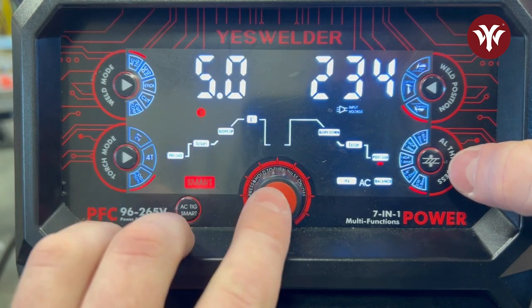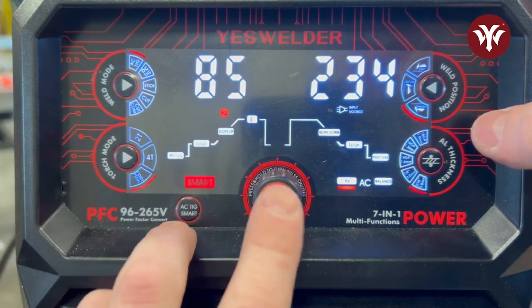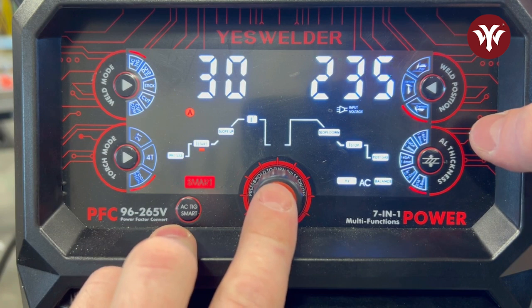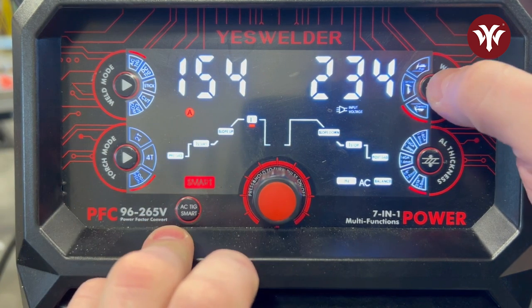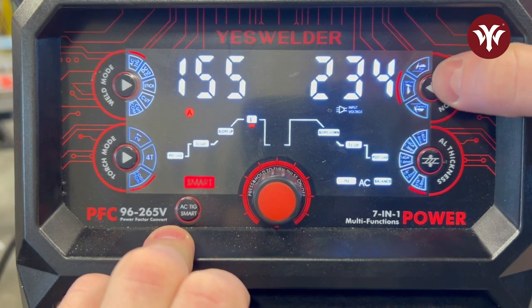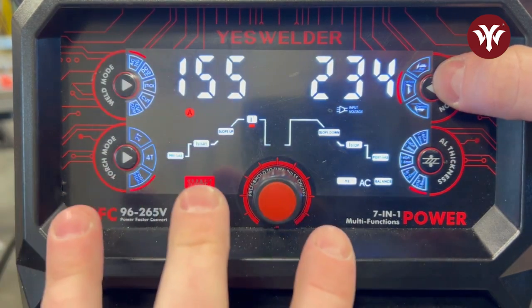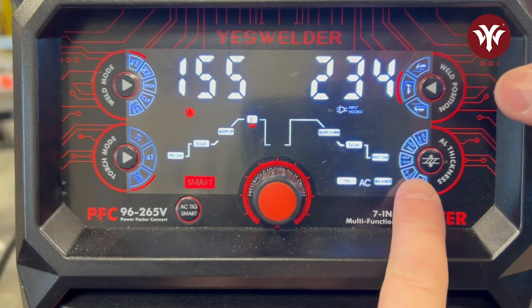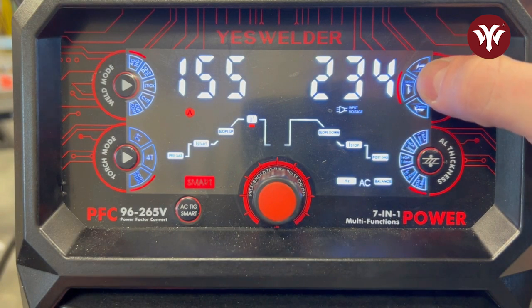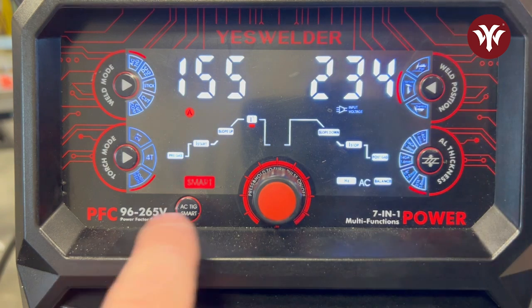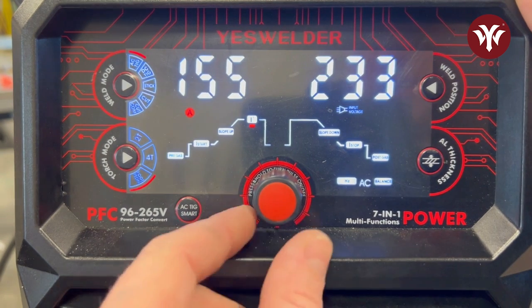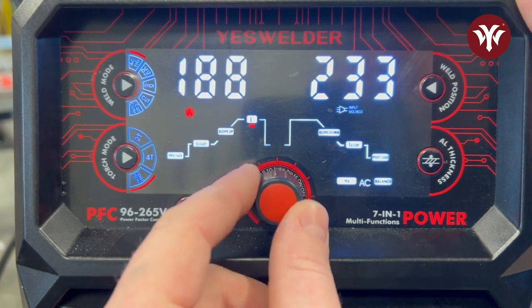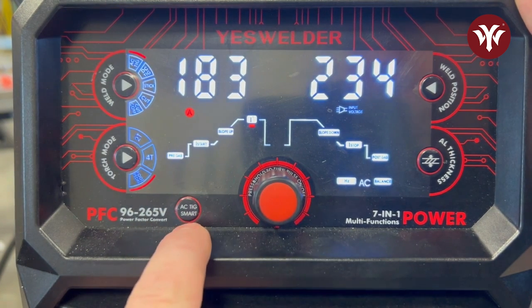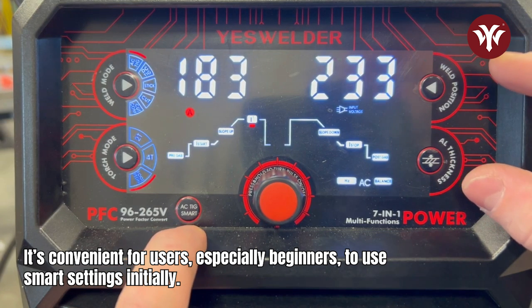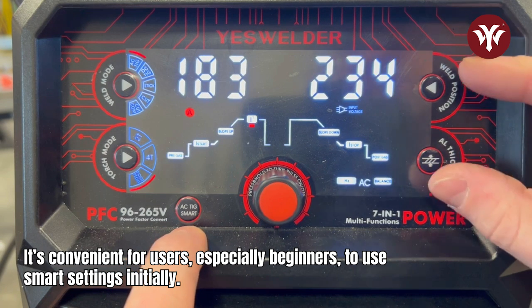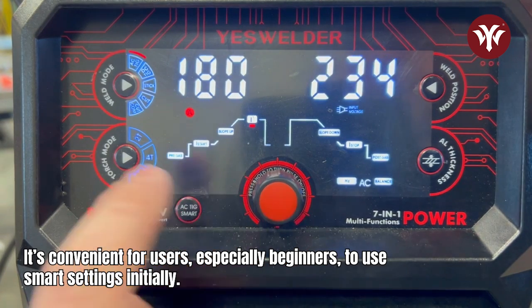Post gas, it did increase as well. Balance is 30, which is good, 85 hertz. Pre-gas, starting current, and weld currents. And as we cycle through your different weld positions, it goes ahead and adjusts all the parameters to have the optimum weld for the given thickness of material and weld position you're welding in. Now, because I've done this for a lot of time, I really just prefer setting everything myself. But if you're new to it, hit the Smart TIG, let the machine preset the values for you, and then once you get comfortable with the actual process of welding, then go in and start playing with things yourself.